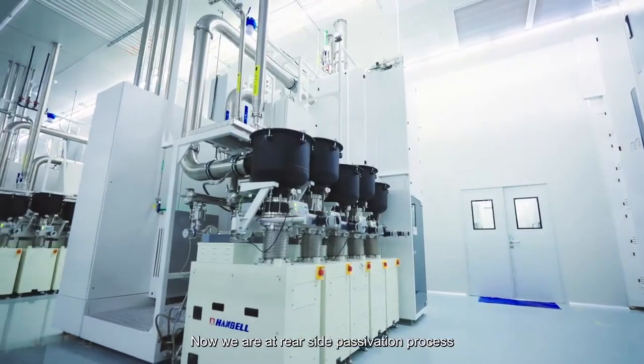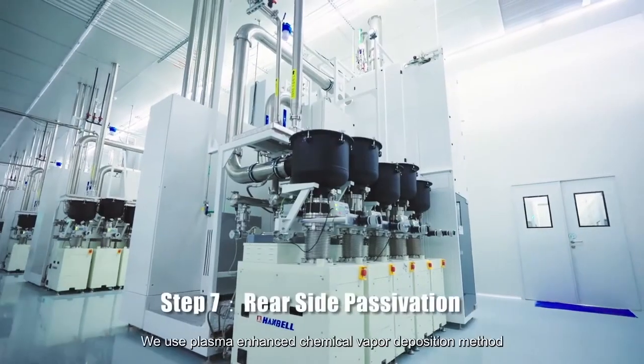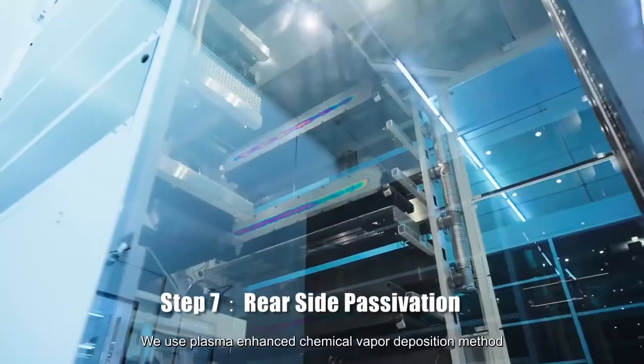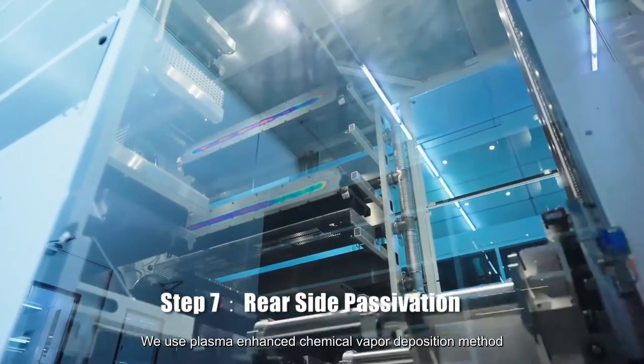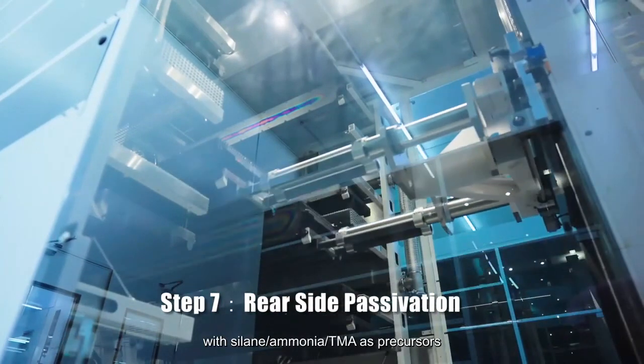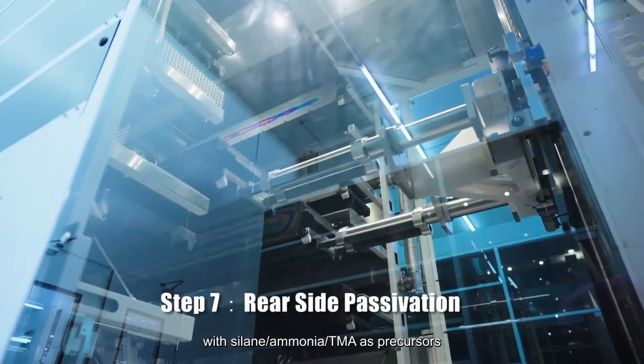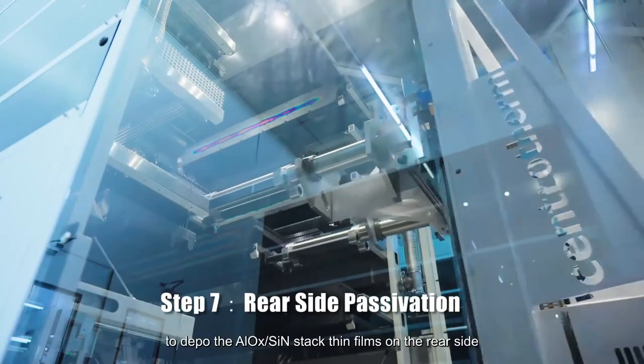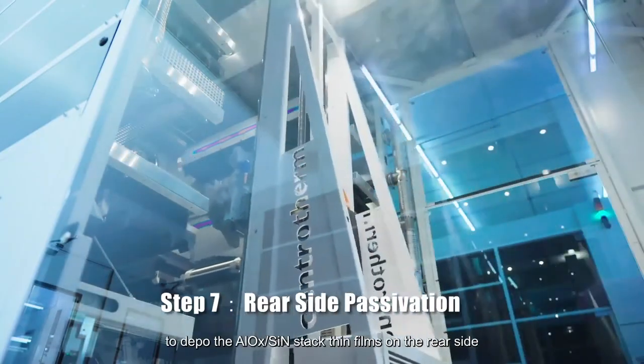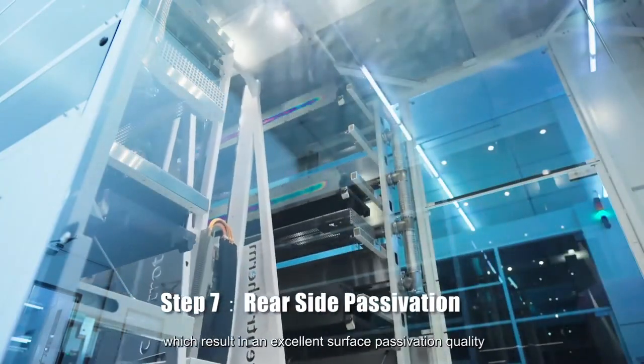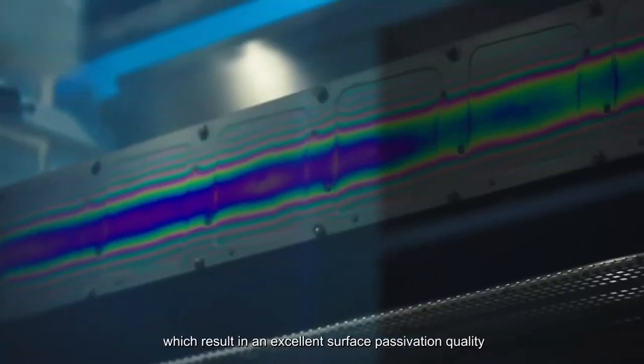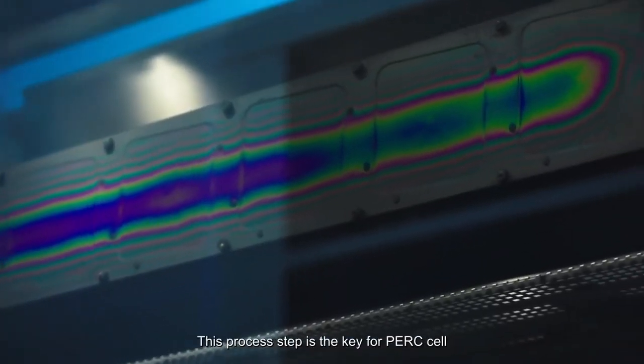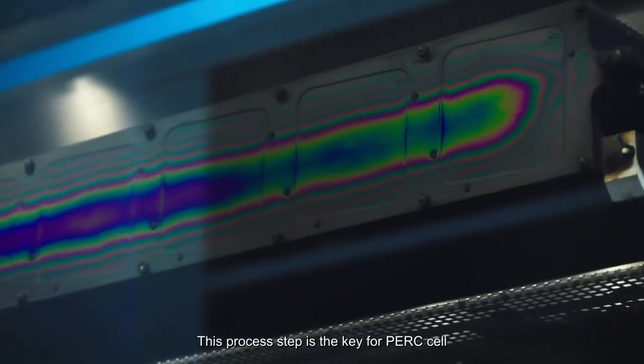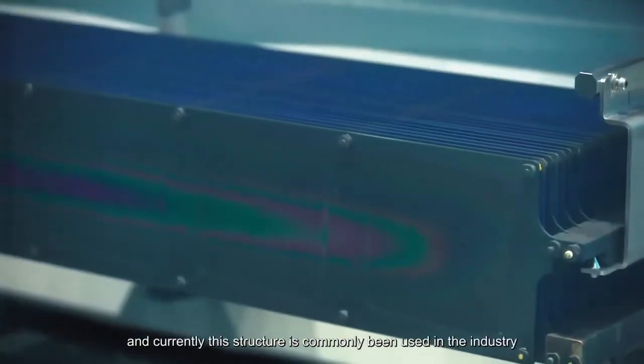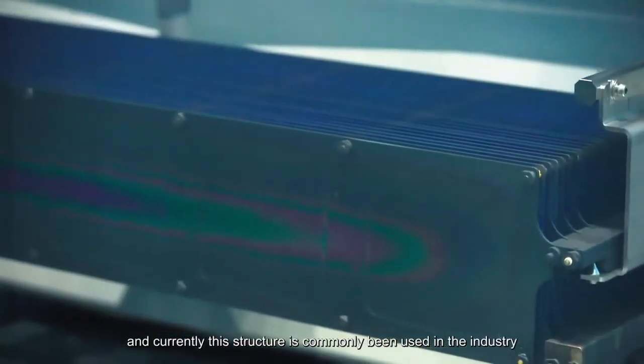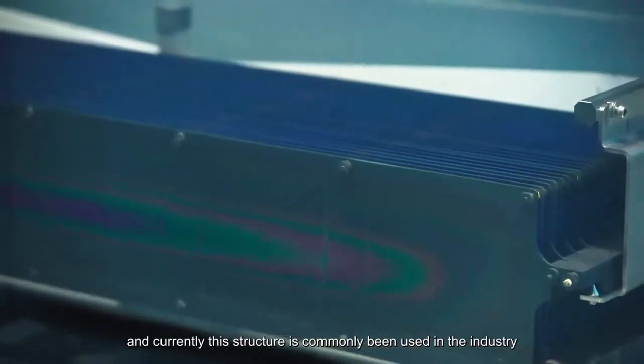Now we are at the rear side passivation process. We use the plasma enhanced chemical vapor deposition method with silane, ammonia, TMA as precursors to deposit aluminum oxide and silicon nitride stack thin films on the rear side, which results in an excellent surface passivation quality. This process step is the key for the PERC cell and currently this structure is commonly used in the industry.